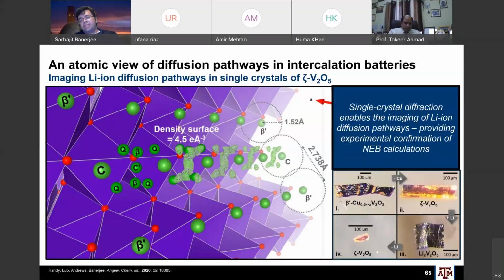We're actually looking at the ions at room temperature as they make their way through the lattice, and we're essentially able to say, okay, here's where the electron density is showing up, and here's where we can refine full lithium sites. Here are areas of diffuse electron density which correspond to low partial occupancies that reflect pathways adopted by the ions through the lattice, right?